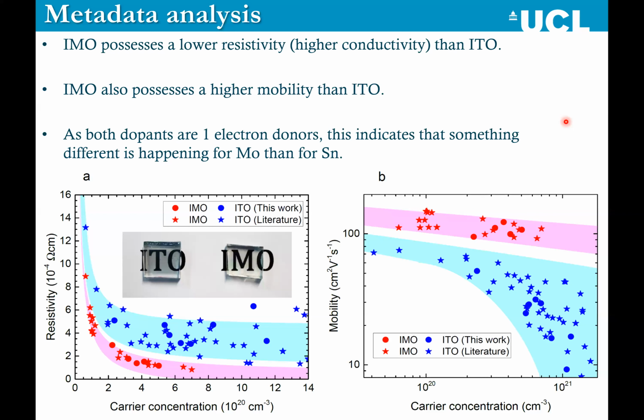So it appears that the field of TCO research and research in general just treated these molybdenum doped indium oxide papers like a weird chemical curiosity. They didn't believe it really. They weren't going into the top level journals. And I think people thought they were just wrong. So the question for us was that, as both dopants are 1 electron donors, why do you have very different behaviors? So what's different for molybdenum than for tin? So this was an open question.